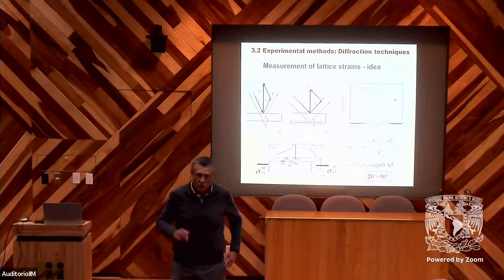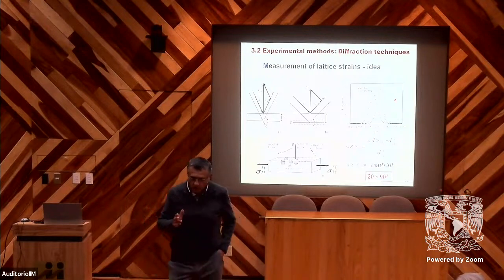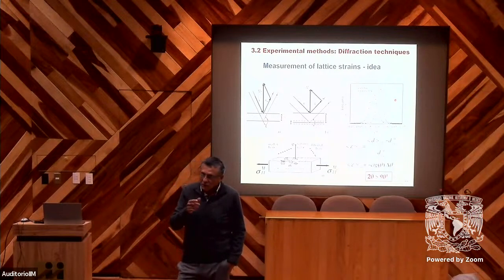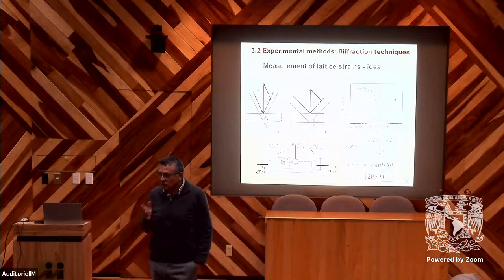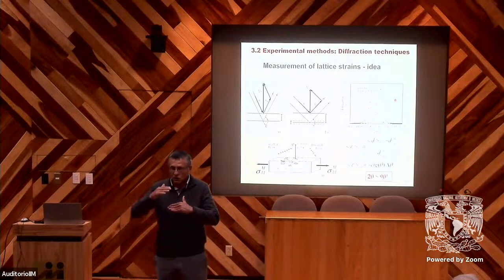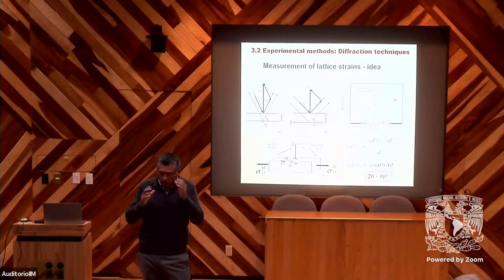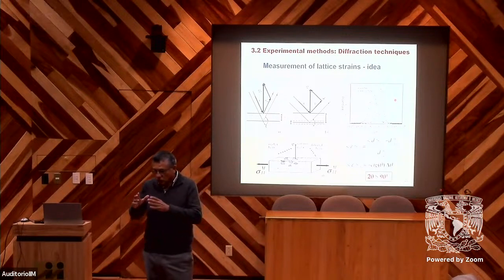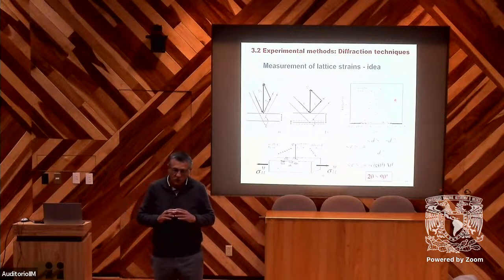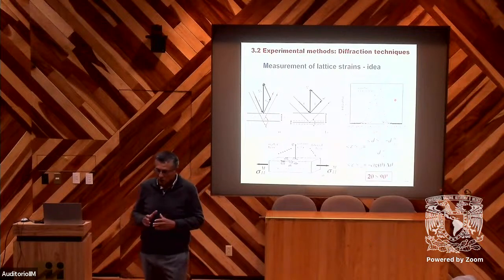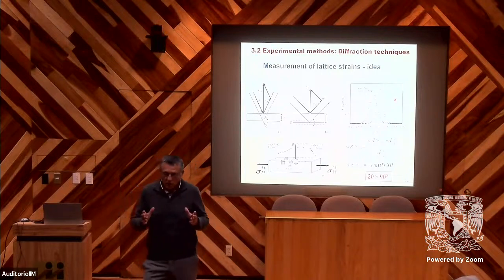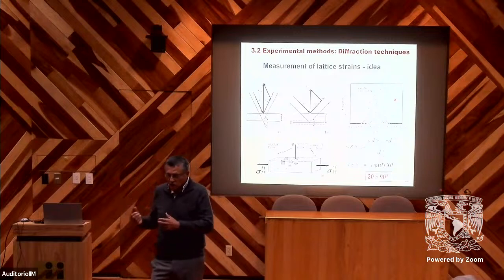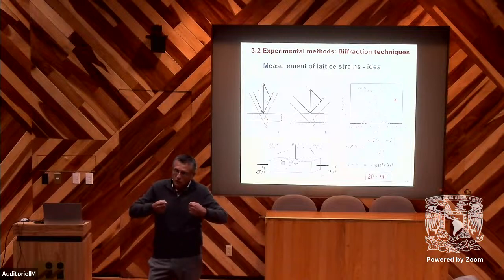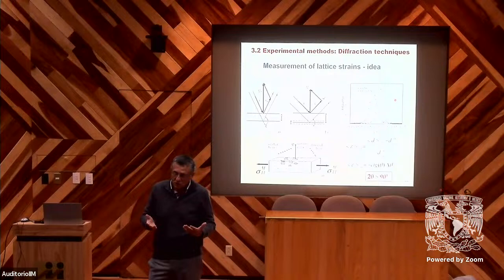What we measure, of course, we need the initial state. It is the problem of the initial state, that means the stress-free specimen. The diffraction method is a relative method. That means you have the initial state and you measure the variation. For synchrotron and neutron, we are inside the matter, so we can have really the triaxiality of stress, sigma 1, sigma 2, sigma 3, all components. For this, in theory, we need the D0. In our study, we start from the initial state and we increase the load and we measure stress. So there is no problem, because we consider that we don't have residual stress.